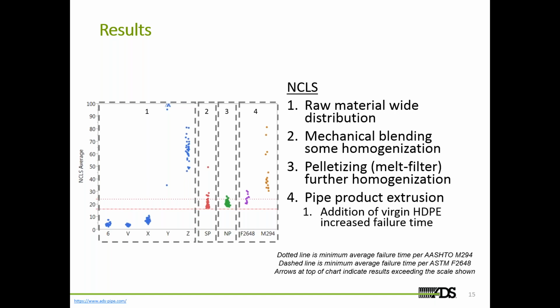The one nice thing about it is that it's consistently poor performing. So as we're bringing in raw material streams, specifically post-consumer recycled material, we have a pretty good idea what it's going to be. It's going to be rather poor performing, but it's consistently poor performing. And in knowing that, we can then blend different raw material streams, whether it's a very good recycled post-industrial material or other virgin materials, to help make up for that poor performing stress crack resistance.